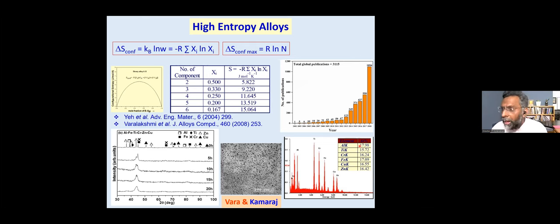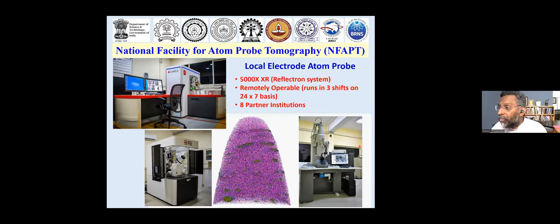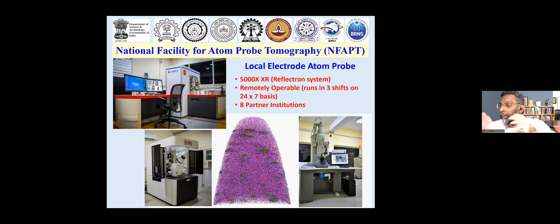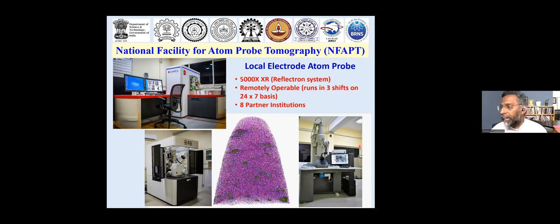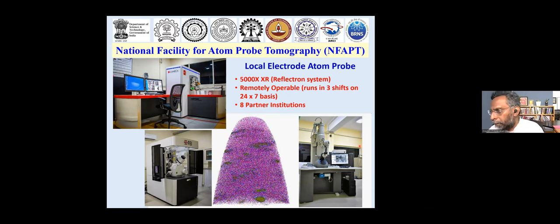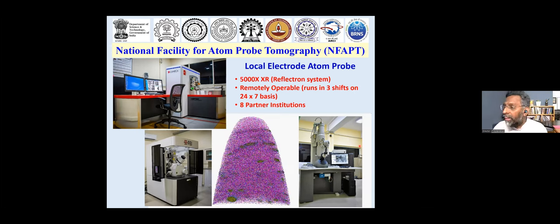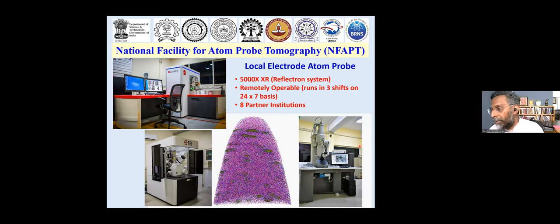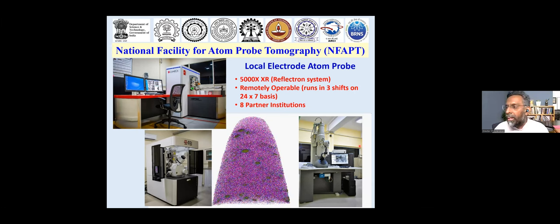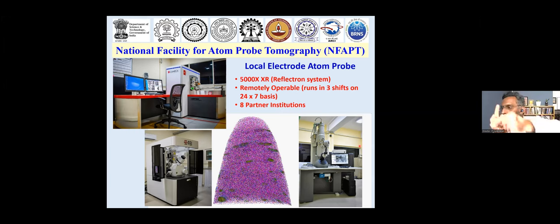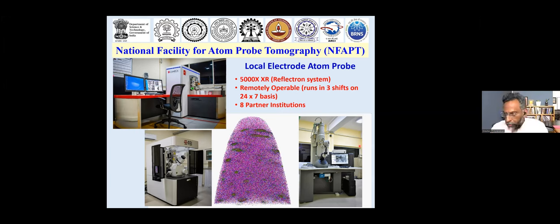And can I go forward and try to see whether this uniformity is at the atomic level or not? There is a technique called atom probe tomography, where you can actually see how atoms are distributed in a material. For example, if you have iron, carbon, steel, where is carbon sitting, where is iron sitting? You can see. For example, here, you can see something rotating in this picture where all the pink dots, each dot is an iron atom. It's a needle kind of a sample, so that's why it looks like a needle.